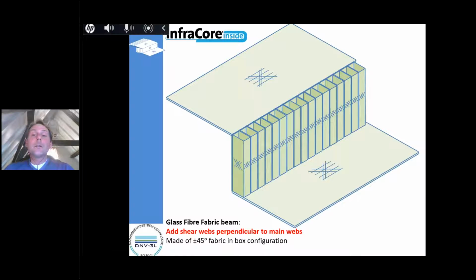And you could think that, okay, this is a nice way of doing that. So you have these inner stiffeners in a certain direction. But what if you need shear stiffeners in the other direction? Then instead of working with a standard non-structural foam block as core material, you would work with these little blocks which have been surrounded by fabric in order to have webs in the other direction. So we can definitely work with webs in perpendicular directions, the main webs.